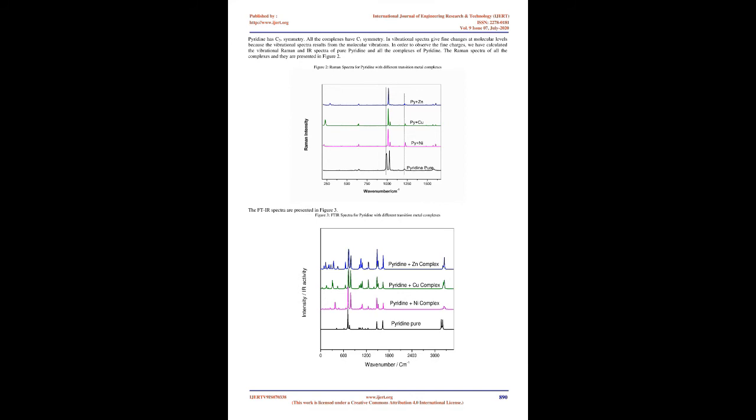The laser Raman setup consists of a 514.5 nm Ar-ion laser delivering about 5 mW intensity as an excitation source, an Olympus 50X objective microscope for proper focusing of the laser beam on the desired portion of the sample in the Raman spectrometer, Renishaw RM1000, having a spectral resolution of 1 cm-1. The Raman spectra were recorded in the range 200-3500 cm-1.